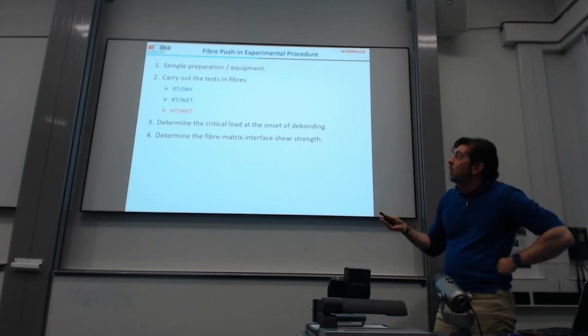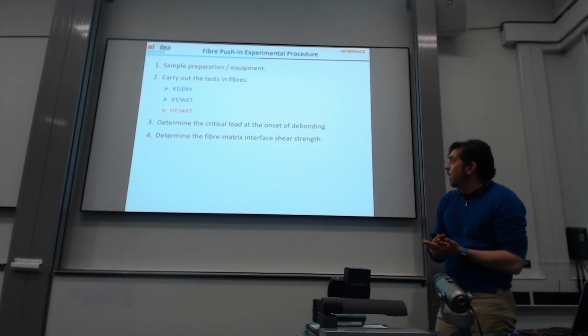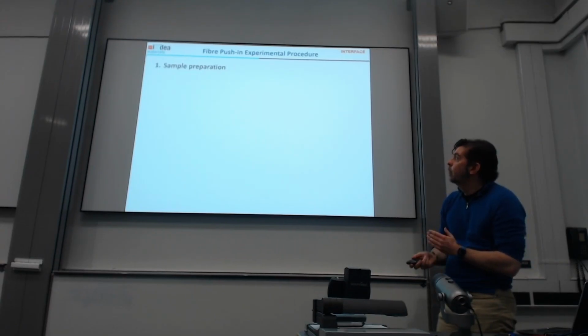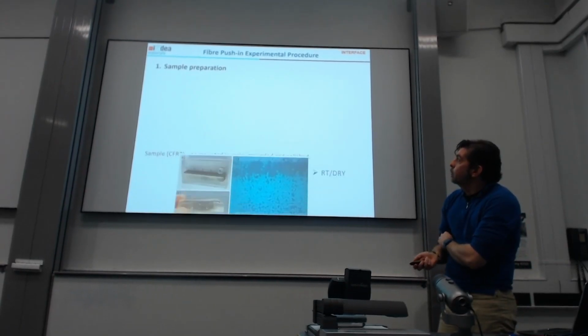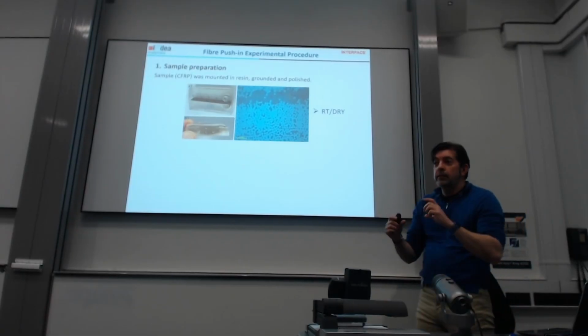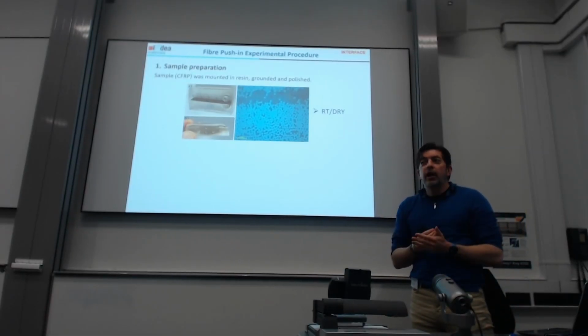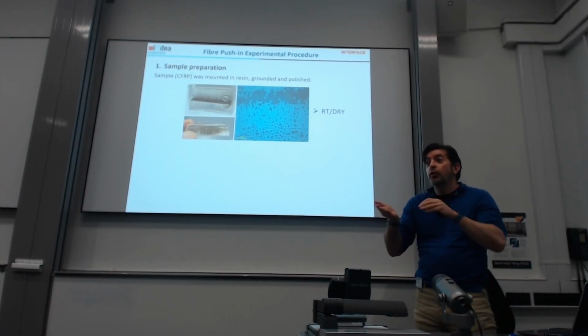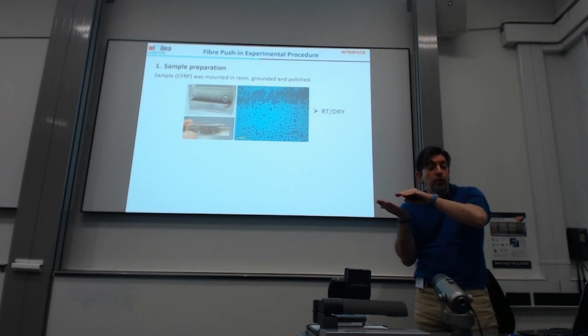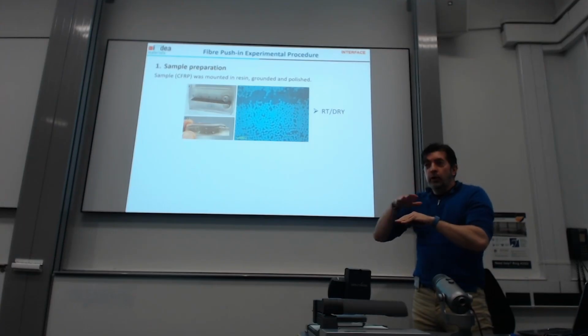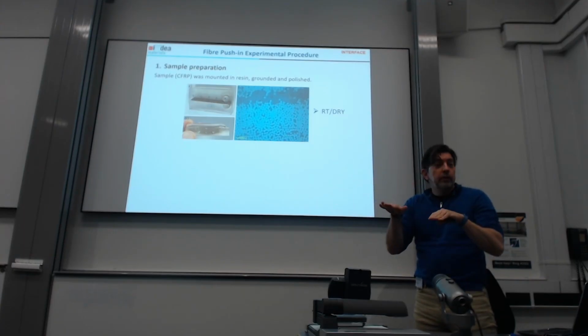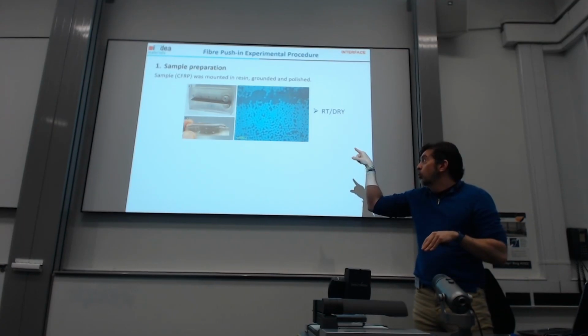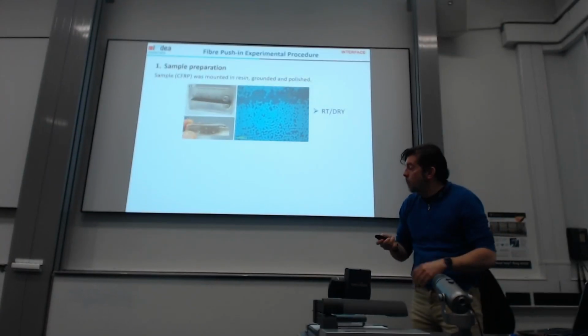Sample preparation, the tests themselves, determining the critical load and the interface shear strength. Sample preparation: sometimes we get these thick samples in a wedge shape, and this is how we're going to test that. So sometimes you need to rectify the back of the sample to make it plane parallel with the surface. You need to have a nicely polished surface, not mirror-like, but you need to see the fibers.